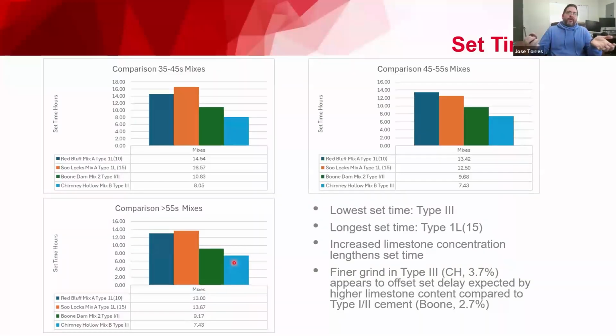It's not really a surprise - type 3 is supposed to set faster. It's high early strength and high set times generally. But we did see the longest set time for us was 16 hours. That's a big question in the grouting world, because unless you're doing 24/7 grouting, your work is kind of dictated by when the grout has set in the hole you're working on, or the foundation you're treating. Like when that's set, you're allowed to keep drilling or moving to adjacent holes. So 16 hours is quite a bit of time.